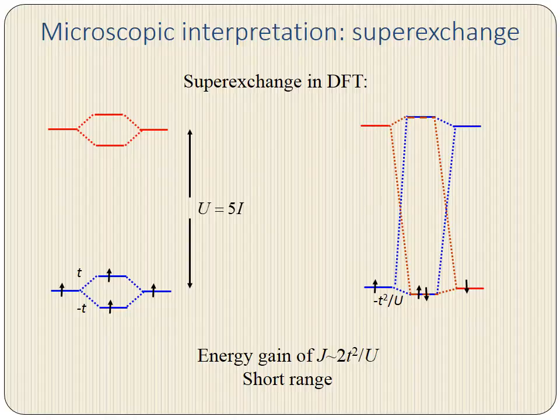Now, if two of your nearest neighbor manganese ions are ferromagnetically aligned, this will lead to a splitting of the occupied levels like so. When you occupy it with 2 electrons, as you see here, there is no net energy gain. On the other hand, for an antiferromagnetic alignment, hopping needs to proceed from an occupied state up to an unoccupied state. This will lead to an overall downshift of the occupied states by the value T squared over U. When you occupy it with your 2 electrons, you get a factor of 2 in front. So, by letting the system become antiferromagnetic, we get an energy gain of 2T squared over U. Therefore, the superexchange interaction typically prefers an antiferromagnetic alignment. This is also a short-range thing, as longer-range neighbors will require additional hoppings, and so the corrections quickly become quite small.